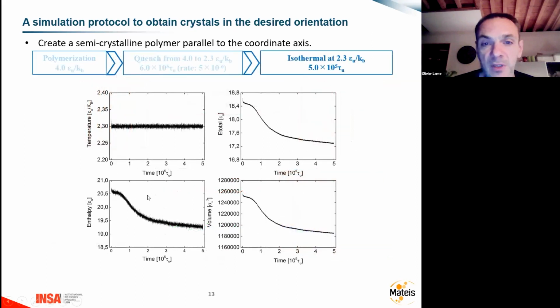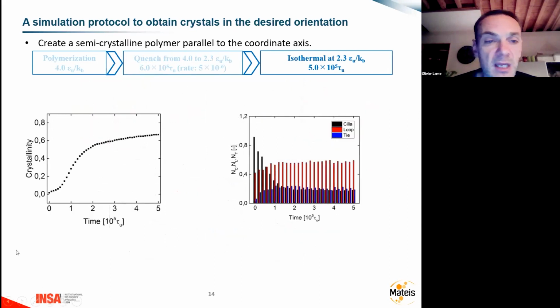So for this system, we have an isothermal crystallization at a given temperature, and we see the crystallization with a decrease of energy and the volume and so on. So it works as expected. And during the increase of the crystallinity, we get again, and this is the interest of this kind of simulation, the complete statistics of any change in the amorphous phase, which is what is invisible in real life. So we can have everything.